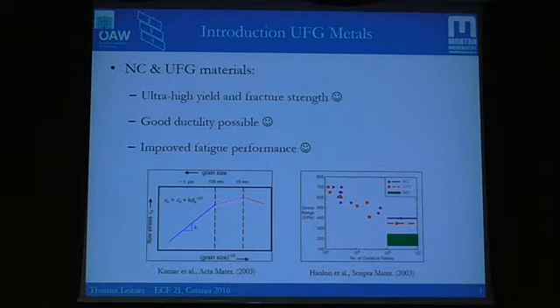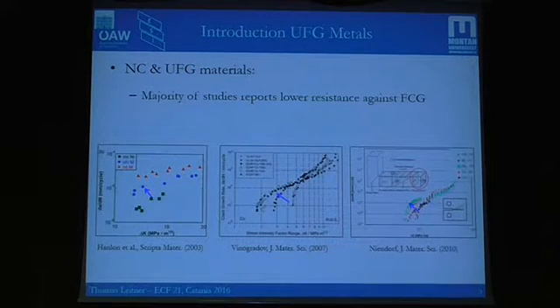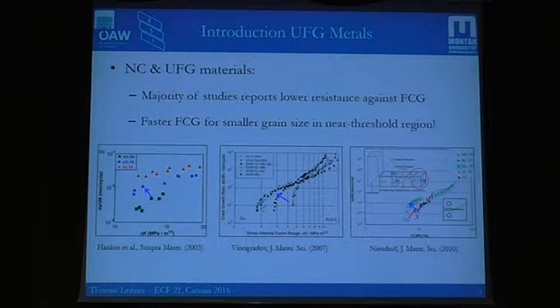So, just a few words on our materials. In our nanocrystalline and ultrafine-grained metals, we get ultra-high yield strength and fracture strength, and good ductility is also possible. Studies also find improved fatigue performance. However, when we look at the fatigue crack growth behavior, the majority of studies report lower resistance against fatigue crack growth and faster fatigue crack growth for smaller grain sizes in the near threshold regime. For example, as shown here for nickel, we see slower fatigue crack growth in microcrystalline nickel than in ultrafine-grained and nanocrystalline nickel.